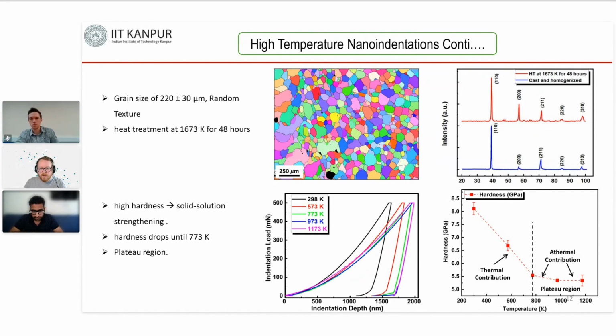Another question from Dr. Nath here, who asks, I think he's trying to ask, is there any post-cast treatment applied to the high entropy alloys? Yeah, we have done the annealing treatment, and at 1000 also we do the phase stability at 1000 degrees Celsius for 48 hours. But even at 1000 degrees Celsius for 24 hours, it is still a cast structure. So we are not able to remove the cast structure at 1000, but we are able to remove it at 1400 degrees Celsius. Okay, got it. Thank you.